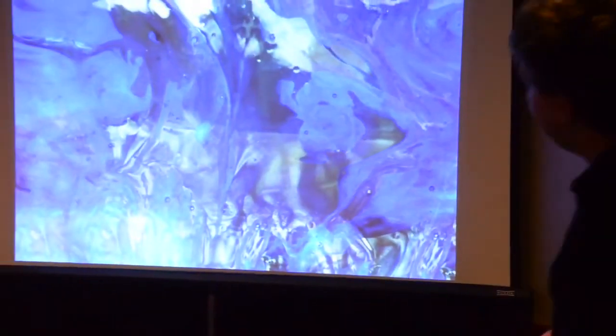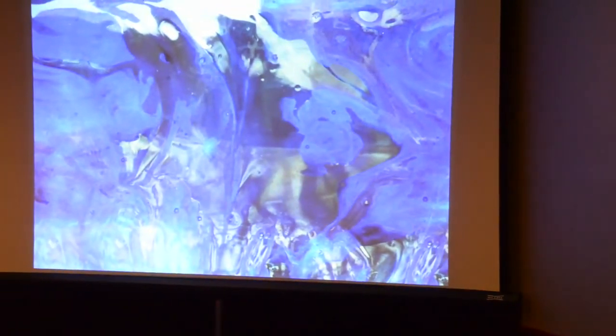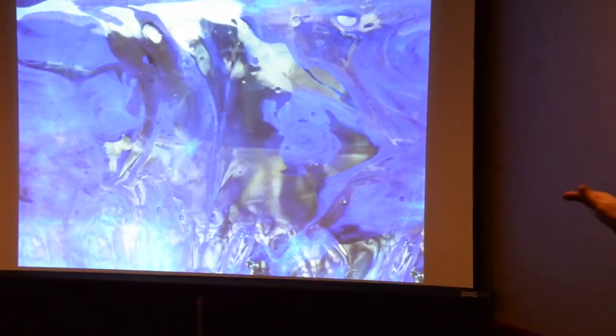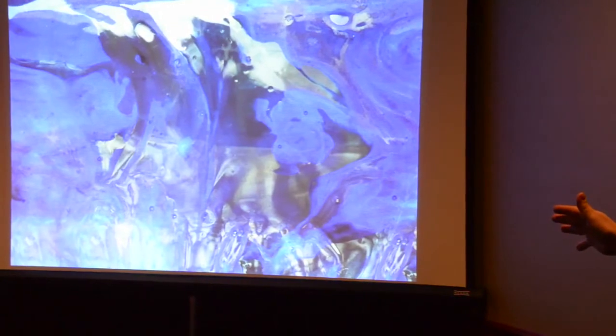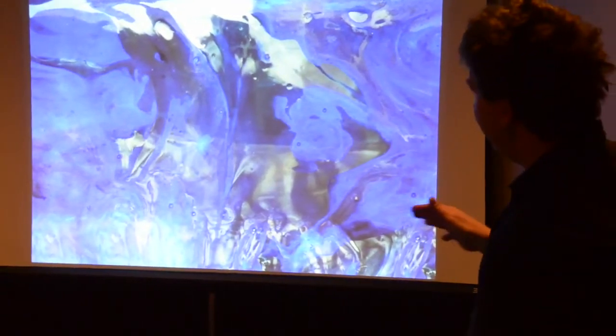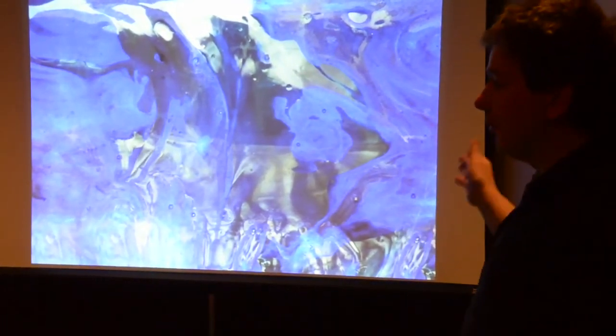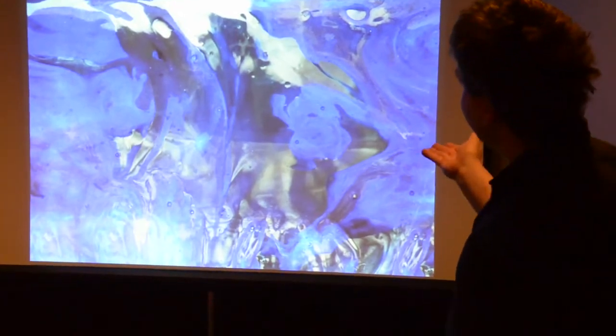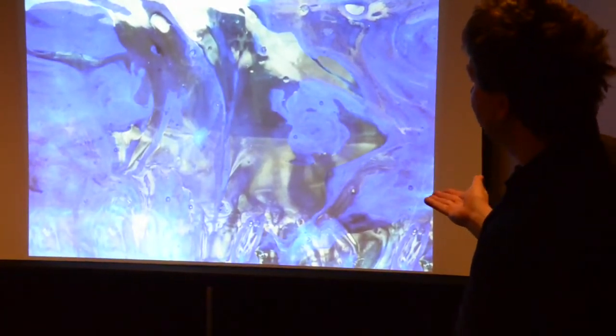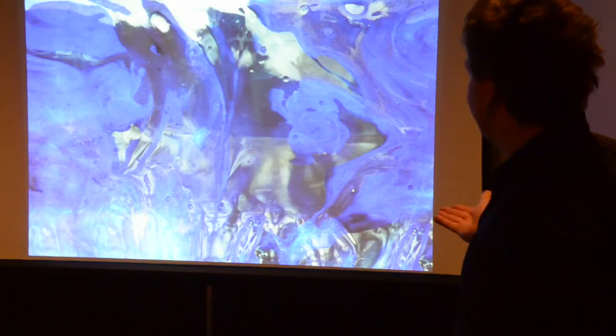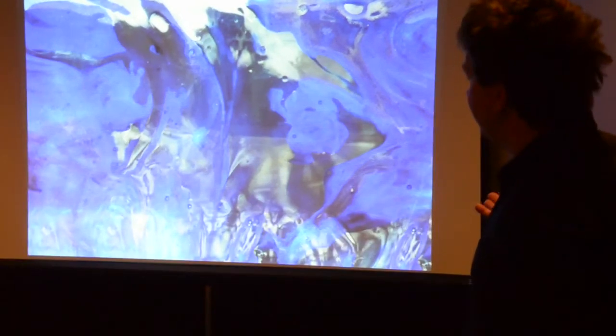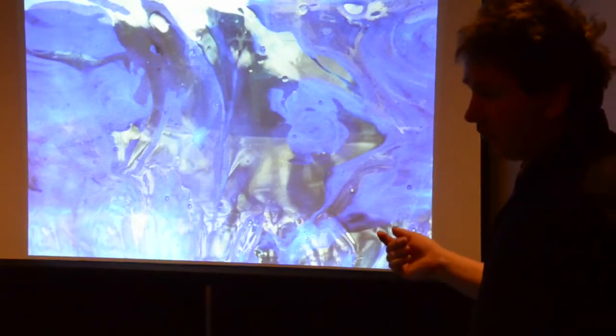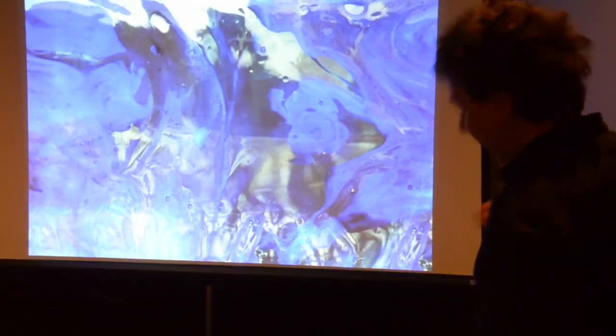This is a sample of blue where I've mixed a silver cobalt blue with a copper cobalt blue, and then I'm putting it in a reducing atmosphere, and that brings out right on the surface, the silver will come out of solution and form that beautiful mirrory surface where the cobalt doesn't do that. So you can intermix colors that look the same to get extremely different results.